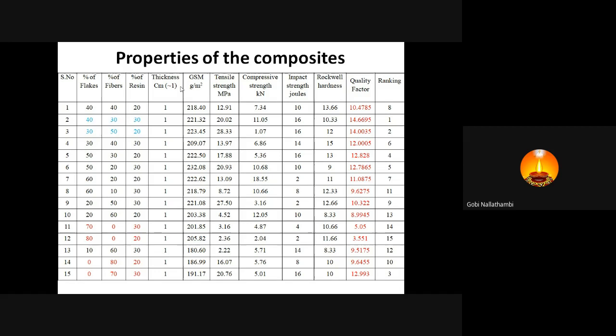So there may be a semi-solid material. Then the semi-solid material may integrate themselves to make a composite. If that is the case, we can minimize the usage of the resin. That is also called a self-reinforced composite. The partial part of the flakes and the fiber can be melted, and the molten area can be used for making the bond, and the residual structure is used to maintain the structural integrity. Then we will get a composite.